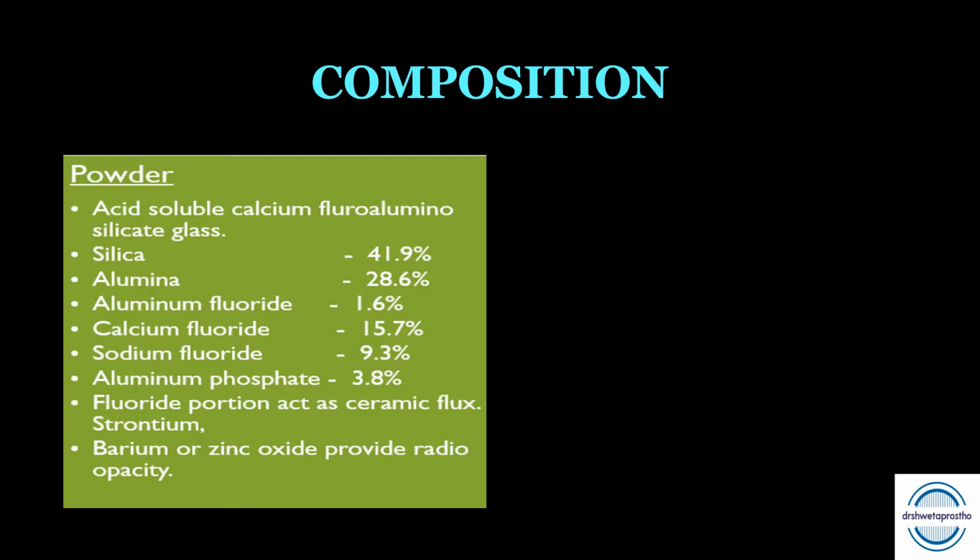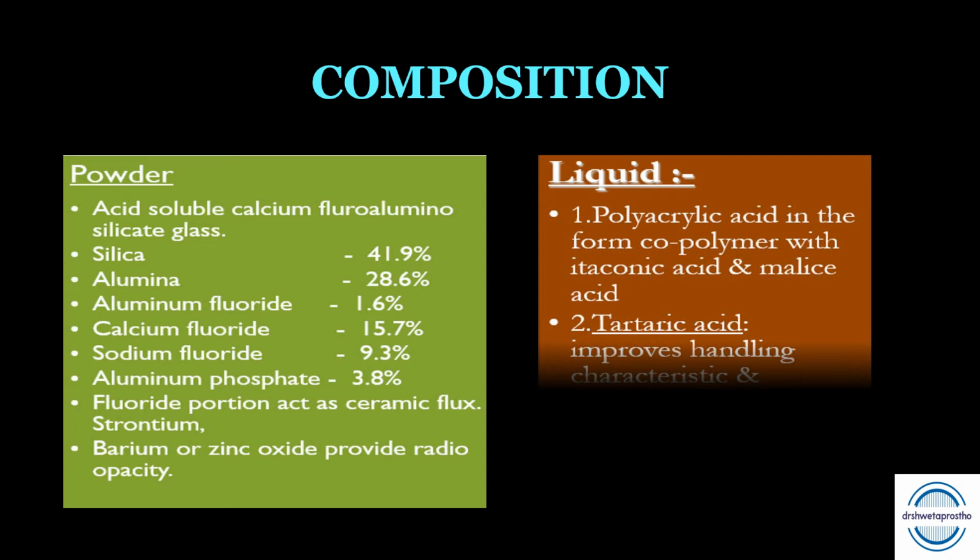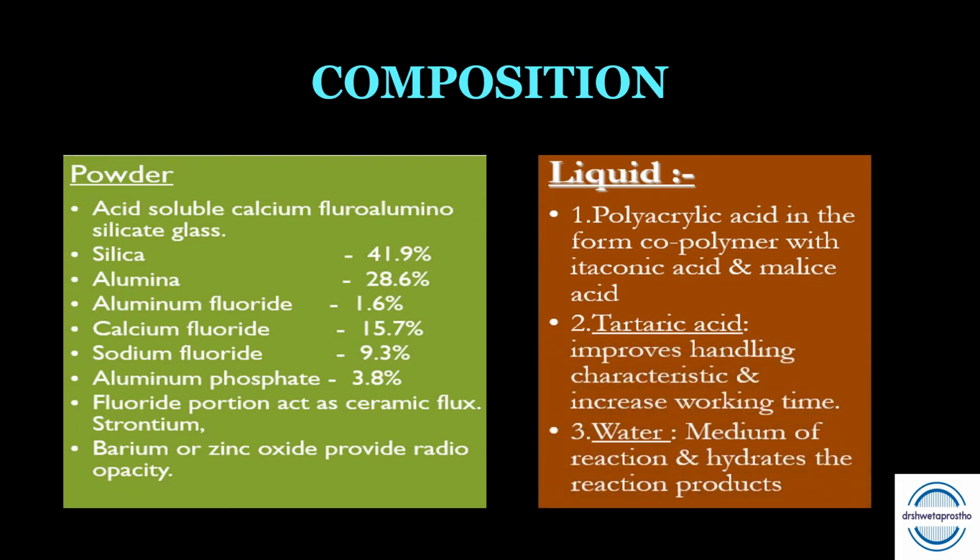This fluoride portion acts as a ceramic flux. So this is important. Then apart from this, lanthanum, strontium and barium provide the radiopacity. Now next is the liquid. Previously it was just a 50% aqueous solution of polyacrylic acid, but now the liquid contains the polyacrylic acid in the form of a copolymer with itaconic acid and maleic acid.